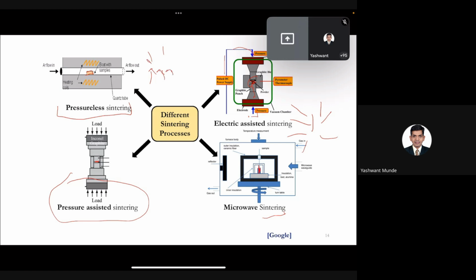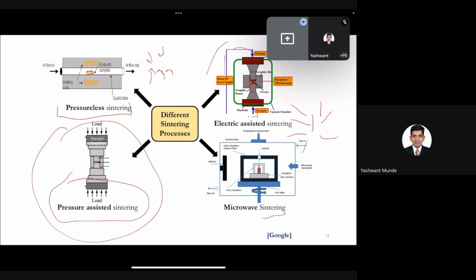So if you analyze these three or four sintering processes, it is very difficult to use pressure assisted sintering and electrical assisted sintering for this process which needs 3D printing and sintering. The question is why? Because when you have cylindrical samples, then it is fine, you can put load on them.